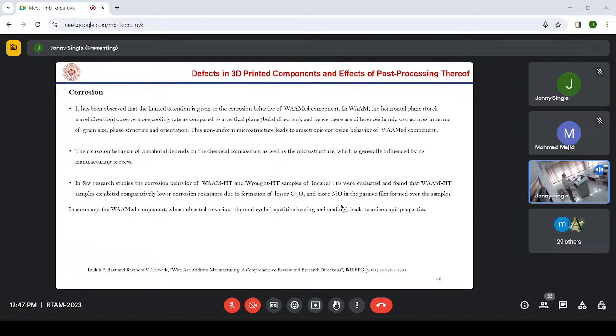Corrosion is also another issue for WAAM component. So to avoid this, the horizontal plane observes more cooling rate as compared to vertical plane. So there are differences in microstructure in terms of grain size, phase structure, and orientation. This non-uniform microstructure leads to anisotropic corrosion behavior of WAAMed component.